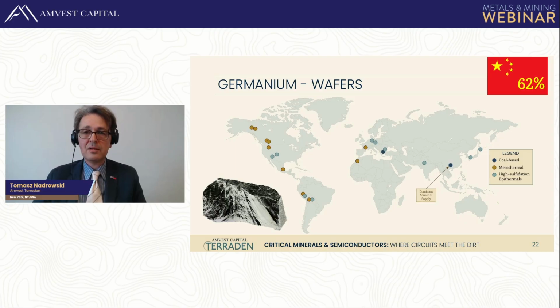Actually, there's one mine that's specifically devoted to germanium in Yunnan. It's called Lincang. And as you see, China controls about 60% of the production of germanium. But it's possible to produce germanium as a byproduct of zinc mines, especially mesothermal zinc, as in Peru or in Canada/Alaska. So there are ways to extract it. That particular mine in China is actually a lignite coal deposit interlayered with some limestone. And a similar deposit actually exists in Bulgaria, but it's not exploited.